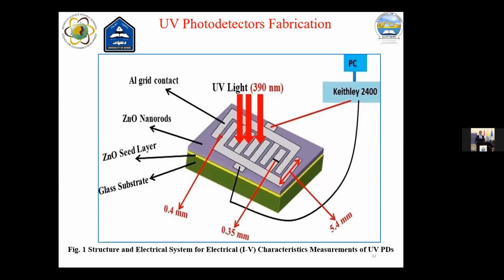After the successful growth of zinc oxide nanorods on a glass substrate by CBD at different substrate inclined angles, we studied all the characteristics, such as morphology and XRD, and we got the optimum substrate inclined angle, which is 70 degrees. I made the UV photodetector for the optimum substrate inclined angle with the high aspect ratio and the high growth rate. This figure shows the structure and the electrical system for the electrical IV characteristic measurement for the UV photodetector.